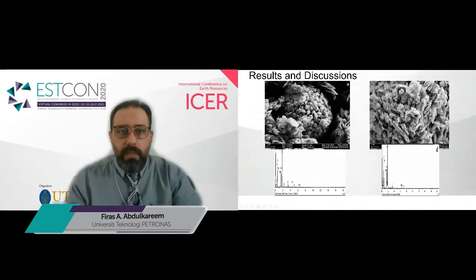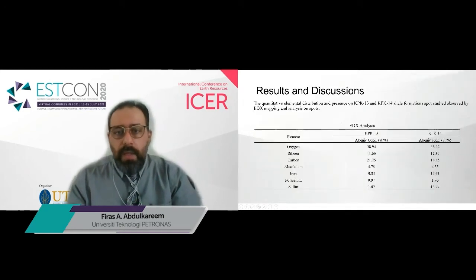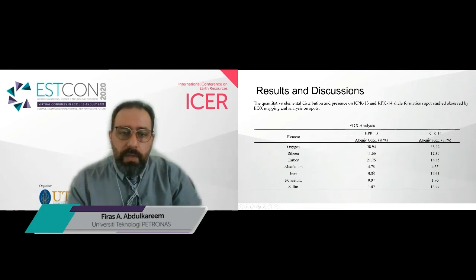On the morphology analysis, we can see a very rough surface on both samples, with some organic matter and clay minerals obviously available, and some cracks and micropores here and there on the surface. On the other hand, with the EDX analysis, as agreed with the morphological mapping, we can see that oxygen represents the highest value of the elemental distribution on the surface of the shale samples, followed by silica and aluminum, which more or less represent the quartz percentage here. And the carbon in the KPK13 is much higher compared to the KPK14 in this case.